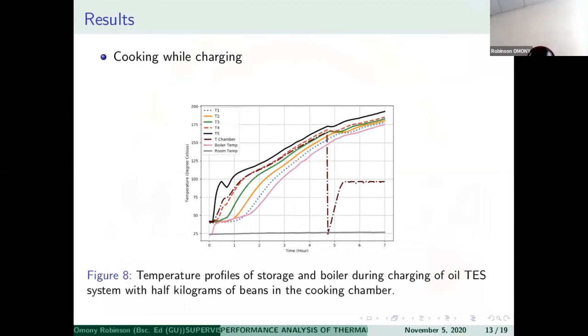Now, in one other experiment, cooking was carried out while charging the TES system, and this is the temperature profile inside the storage. But of course, this was carried out with the oil only. But a similar test was also carried out with water, and I must admit that this system was so good, with the ability to be used for cooking during charging.